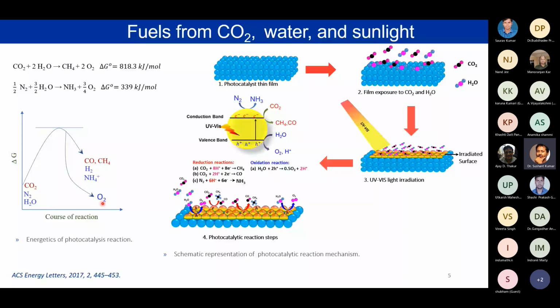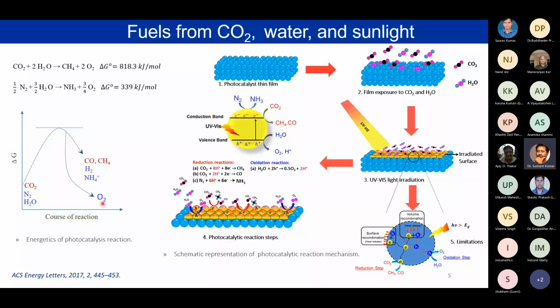So now, when I was talking about the surface phenomena of this reaction, I told you that there is a lot of drama that goes on inside the catalyst. And when we look inside, what is this? This is surface recombination. To explain this, what has to be understood is that within the catalyst there are certain sites at which the electron and hole recombine and are lost. Since they don't get to reach the surface of the semiconductor or the photocatalyst, they don't interact, they don't react, and they don't participate in the reaction.